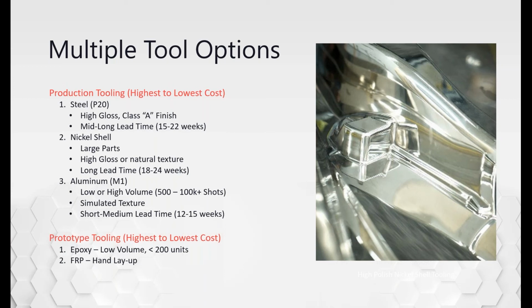Nickel shell, we'll use nickel shell when the part is really large, those 8-foot, 10-foot, 12-foot parts. If you were to produce a mold out of billet aluminum or steel, just the weight of the block would be too heavy for our presses to pick up and our material handling equipment to move the mold around the plant. So nickel shell reduces the weight significantly of a mold. What you end up with is a shell of nickel forming the cavity and or core, and then it'll be either like an egg crate construction casting of aluminum, and it may even be an egg crate construction of plywood to make up the chase of the cavity and core.